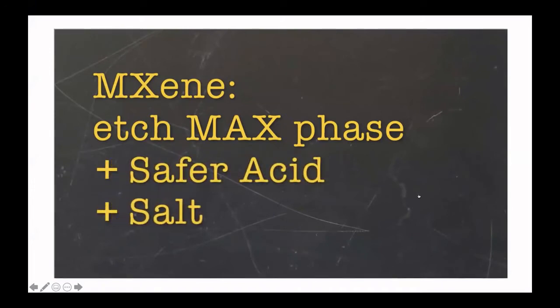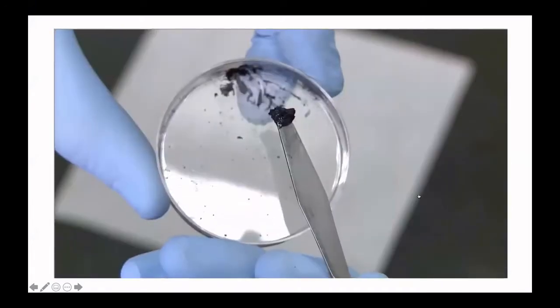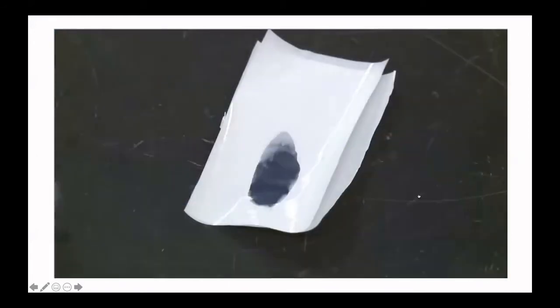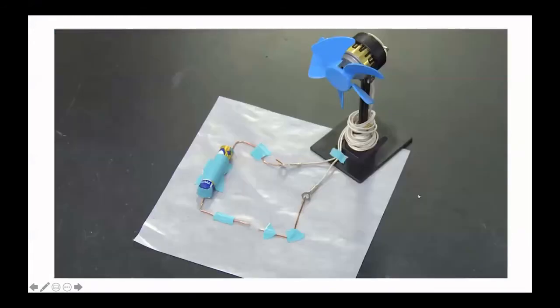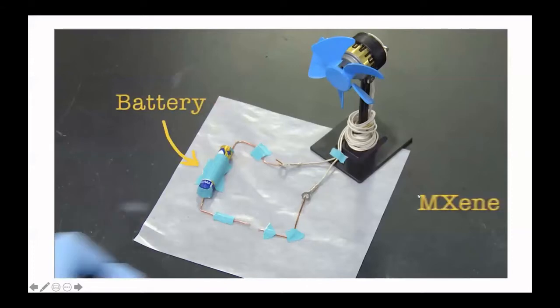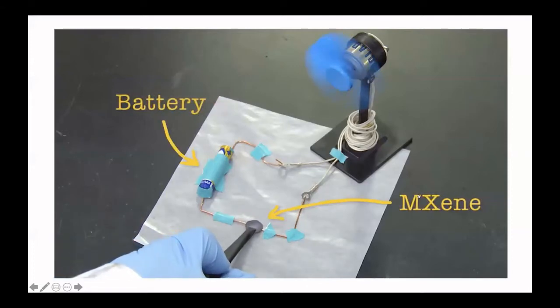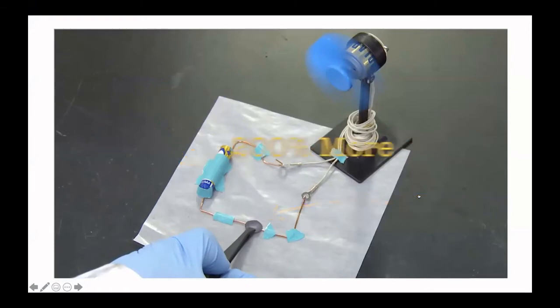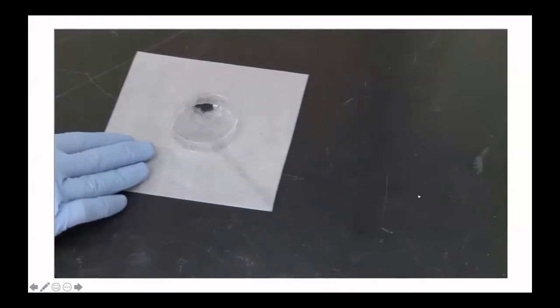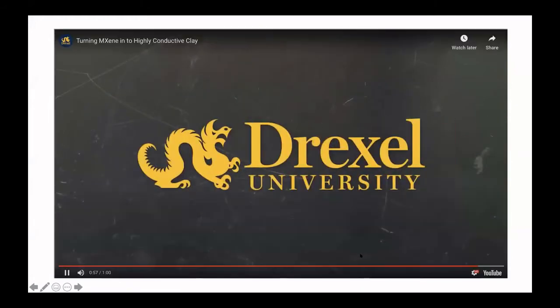Now, we simply react MAX phase with an etchant made from a much safer acid and a salt, and after washing, we're left with a clay-like material that we can shape any way that we want, even rolling it out into a film. After drying, it's highly conductive. Not only is the process easier and safer, but electrodes that took us only 5 minutes to roll out have shown a 200% increase in capacitance over our previous reports. Sometimes the simplest ways are the best, and it's one of the many great things only happening at Drexel.